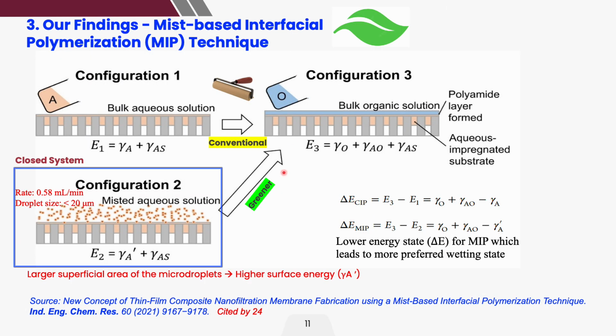Here I would like to present our key research finding based on the mist-based interfacial polymerization technique, in short form MIP technique. Configuration 1 and configuration 3 are the conventional IP process, where you pour the aqueous solution on the membrane surface, followed by aqueous solution removal using a rubber roller. Then you introduce the second organic solution. Once the second monomer reacts with the first monomer, it forms the polyamide layer.